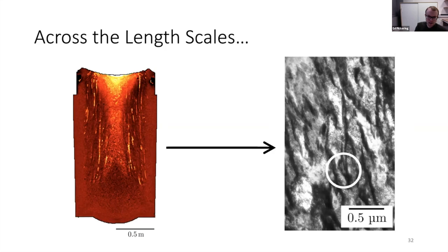So this was a case of looking at what's inside those channels, and in this particular case, working out what the ferrite carbide orientation relationship was. That's very much across the length scales.